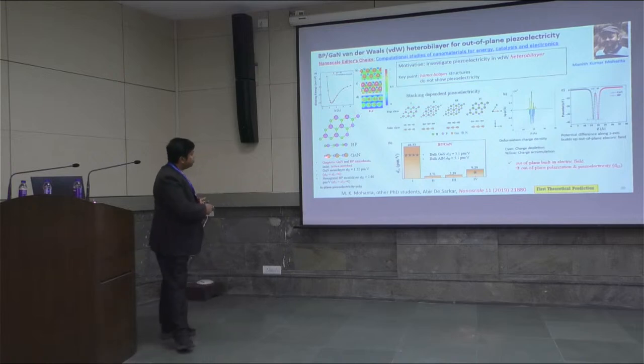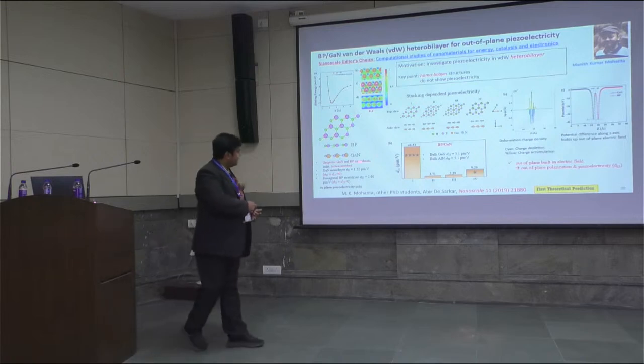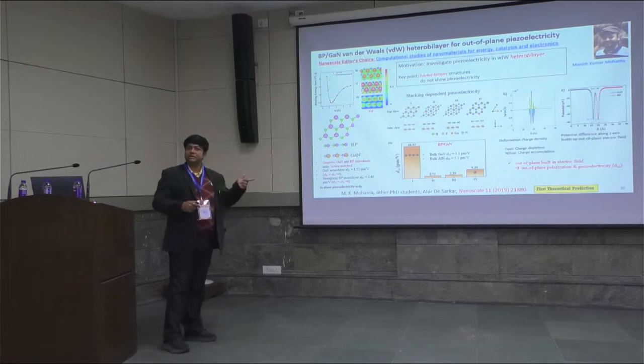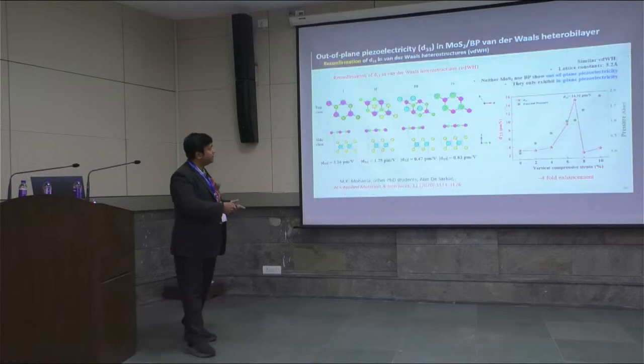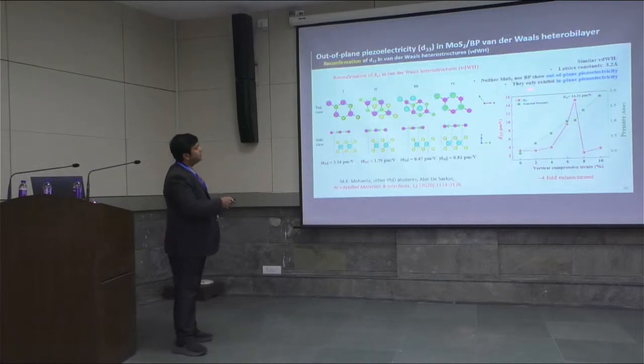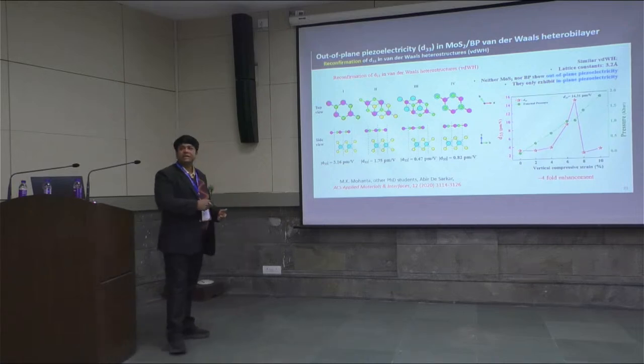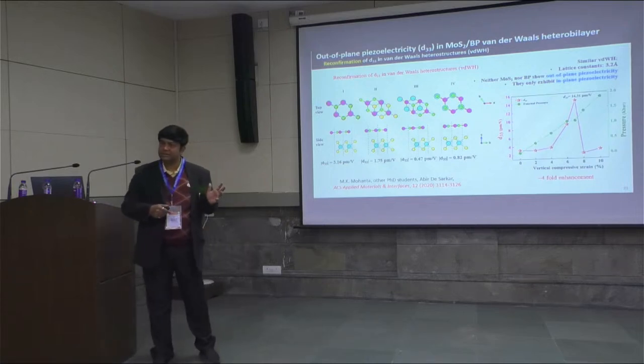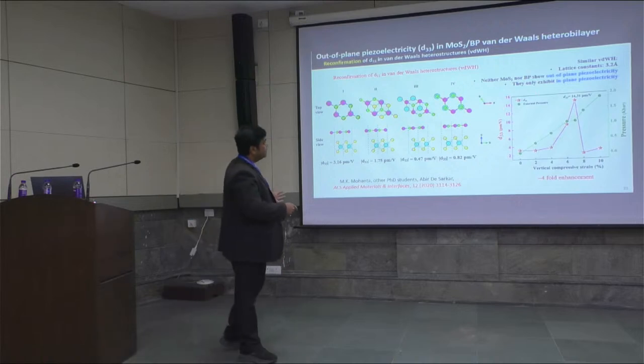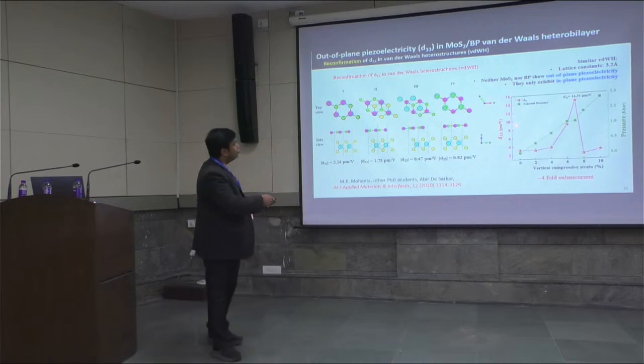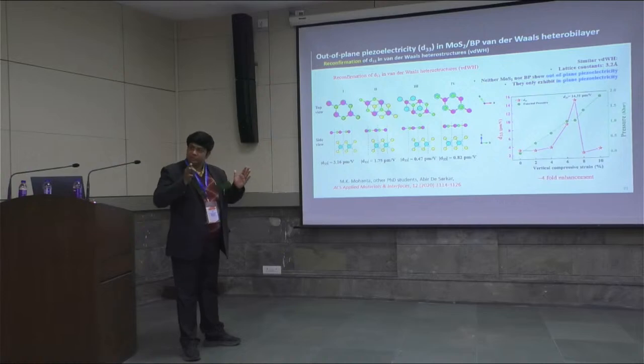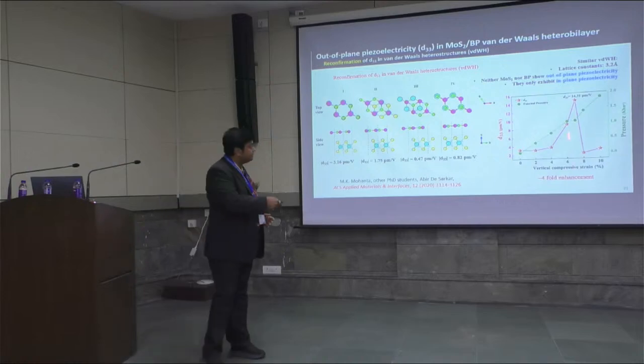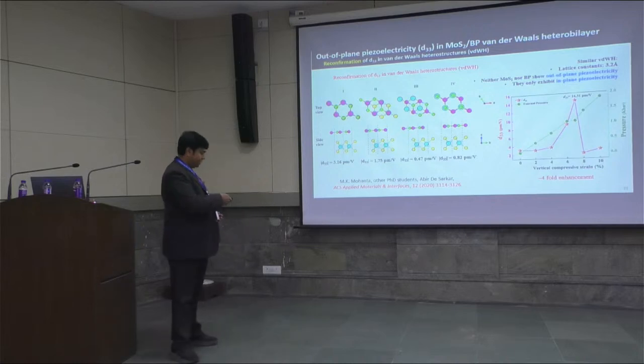So what we have done is that we have replaced gallium nitride by a monolayer which is similar to gallium nitride, close in the lattice constant to boron phosphide and gallium nitride. So that's what we have done here. We have replaced gallium nitride by MoS2, molybdenum disulfide, and we find that our understanding is reinforced in this van der Waals hetero bilayer as well. And here what we find, again, interface driven properties. So if the two monolayers are subject to a vertical compressive strain, there's a four-fold enhancement in the out-of-plane piezoelectricity.